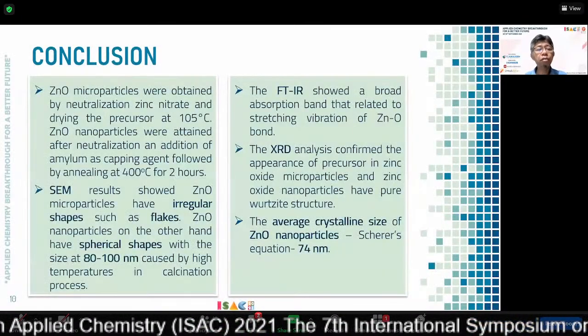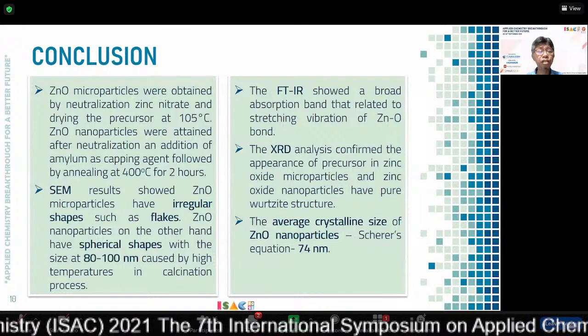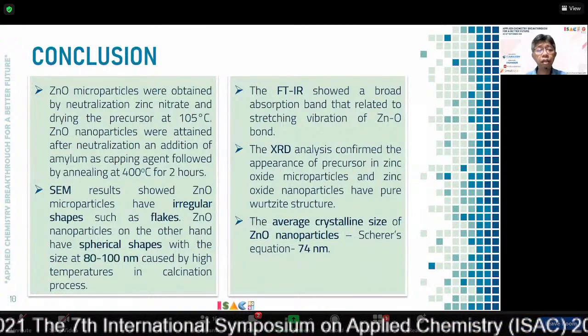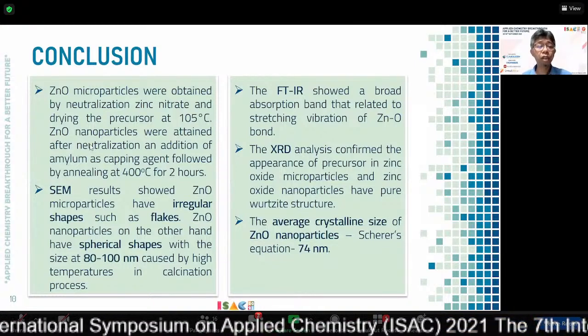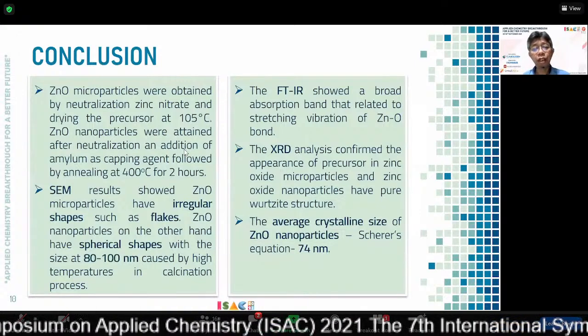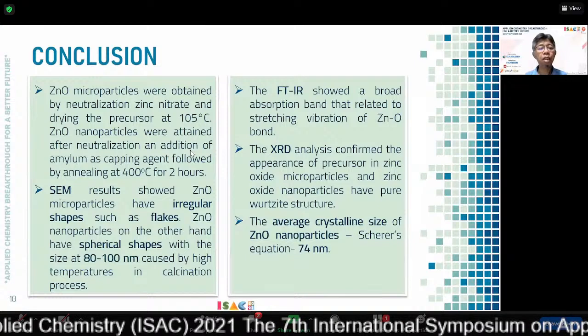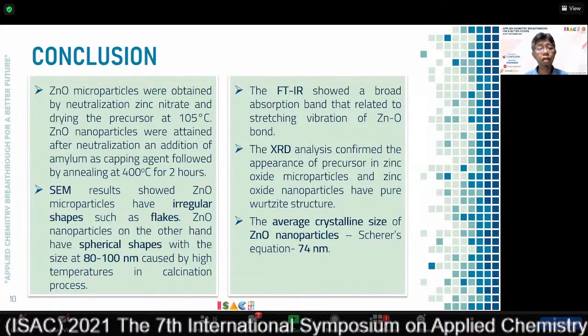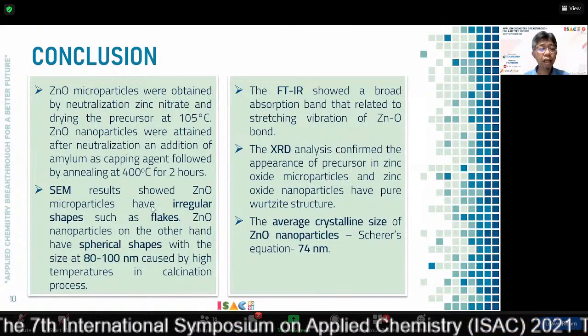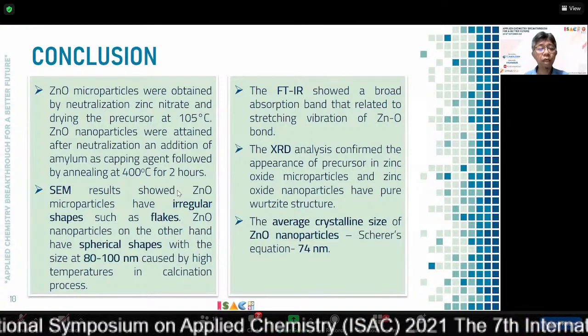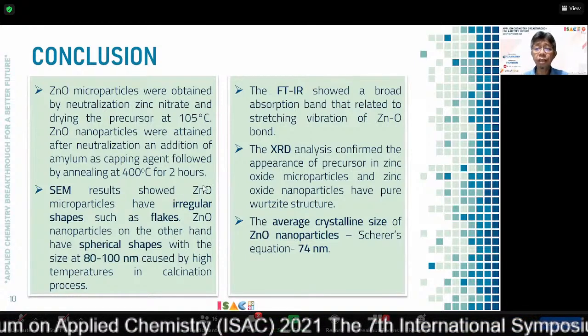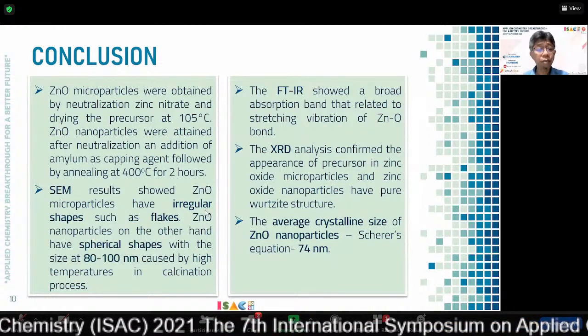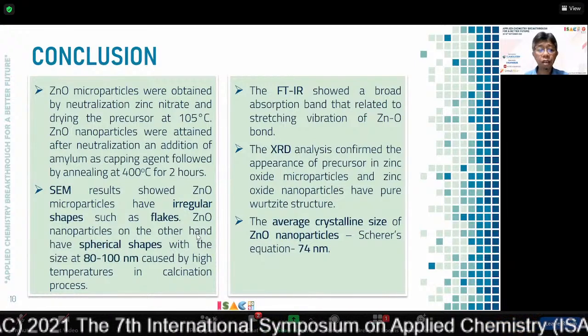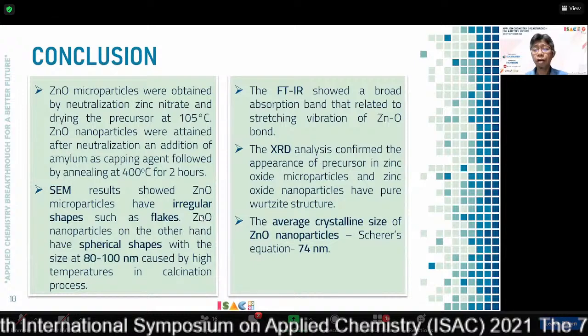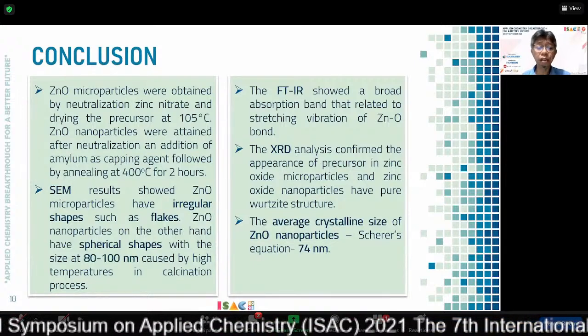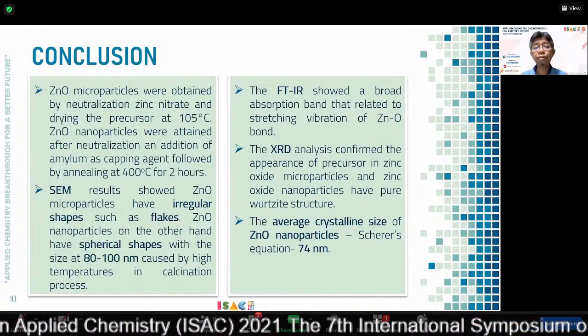So in conclusion, zinc oxide microparticles were obtained by neutralization of zinc nitrate and drying the precursor at 105 degrees centigrade, while zinc oxide nanoparticles were obtained after neutralization and adding the capping agent, then heating it up to 400 degrees centigrade, producing zinc oxide nanoparticles. The SEM also shows that microparticles have an irregular shape, such as flakes. On the other hand, the zinc oxide nanoparticles show a spherical shape with a size of around 80 up to 100 nanometers due to the calcination process.